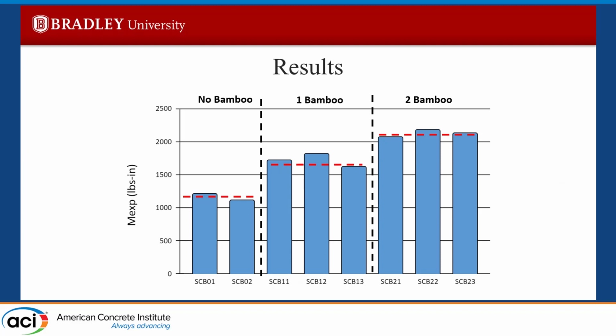So what did we find? So our experimental moment is on the left side, and then our specimen names are right there. We had an average around 1,100 pounds per inch for just regular sulfur concrete, but as you increase to 1 bamboo, the experimental moment did increase by around 50% to around 1,600, which is a big jump. And then from one bamboo to two bamboo, it reached a 25% increase from 1,600 to around 2,100.